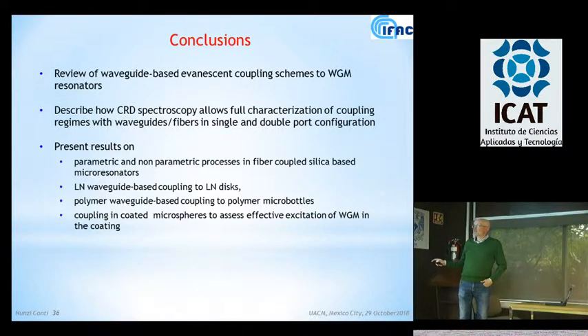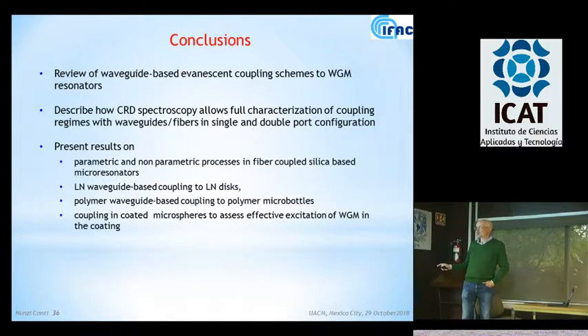So stressing the work of Gabriele Fugenti on cavity ring-down spectroscopy, also in the double port configuration, which was able to assess the coupling conditions and the coupling regimes. And then I presented results on parametric and non-parametric processes in fiber coupled silica-based resonators, results on coupling a lithium niobate disc with a lithium niobate waveguide, and finally, more recent results on polymer-based resonators.